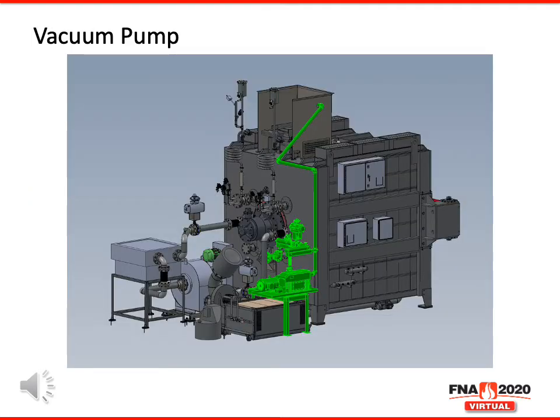So one of the first options that we have to add to a nitriding furnace is a vacuum pump. Now, these furnaces are not designed to be a true vacuum furnace, but we can use the vacuum pump to help on the purging steps, to speed that up and to help ensure that we've got the furnace fully purged of any air or oxygen that could be in the system before adding any ammonia.